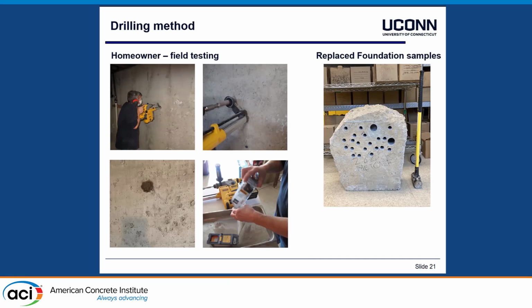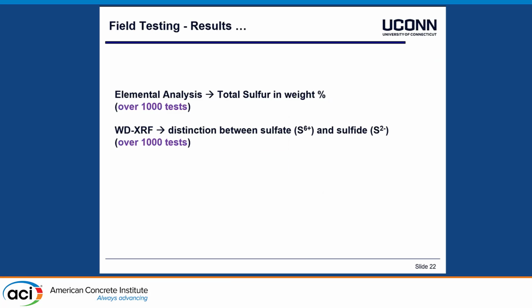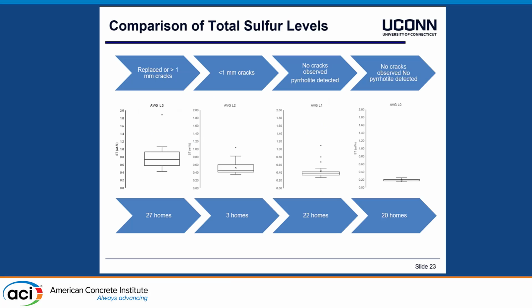And then this powder collected with a vacuum drill gets brought back to the lab, analyzed, and further prepared if we need to crush it finer, for example, and analyzed. So far, we have done over 1,000 tests in terms of total sulfur and over 1,000 tests in terms of WD-XRF investigation. And then with this database, you can start categorizing certain phenomena or certain conditions in the field.